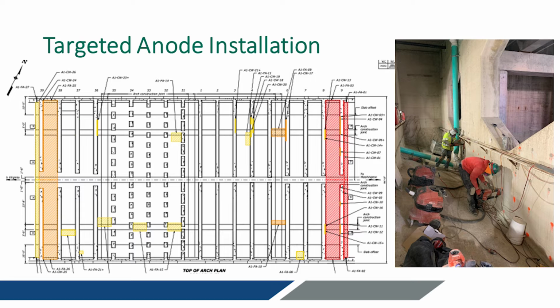So clearly, if you're comparing this to when they were first bidding this project, they were looking at CP over the whole structure. This is quite a reduction of that need, and obviously you don't need to put it everywhere if it's not corroding. And so you can see here, gentlemen on the right, effectively doing the corrosion potential survey, they can identify where those anodes need to go. And here they needed to put some along the bottom of this crosswall, but not in the upper parts, just where those orange dots are. So we're really being efficient with our cathodic protection.